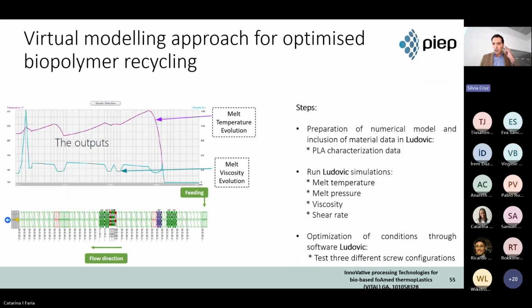So Ludovic, I will not go too deep on the software side, but Ludovic is used, at least it was developed, for fossil-based materials, and it is used to simulate or at least try to anticipate what's happening in the compounder. So we need to have the characterization of the material. We put the material data on the software, and then through the screw configuration and the processing parameters we can anticipate what's happening with the material during the extrusion processes.